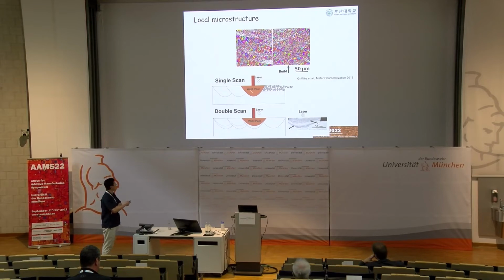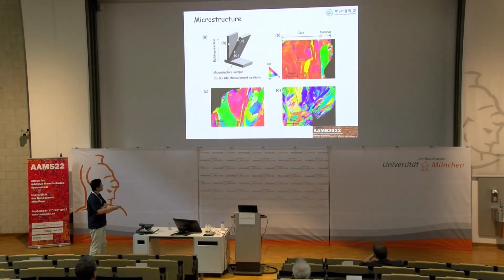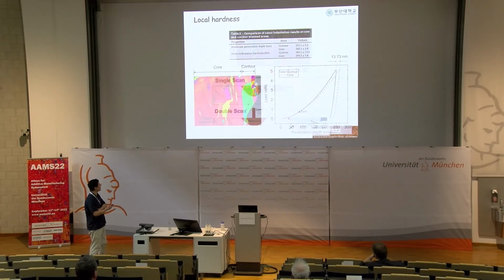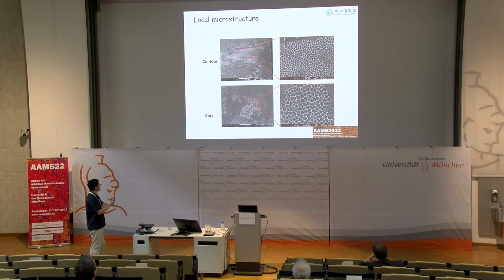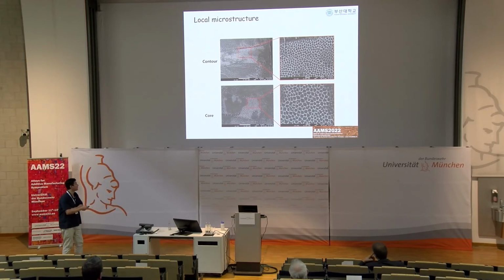That was our hypothesis, but the reviewer raised one question, that this might be due to the molten powder. Yes, that's possible, but we still believe that there is a difference in the solidification rate, because we checked the solidification cell size and we found that near the contour scanning region we have much finer solidification cells in comparison to the core part.